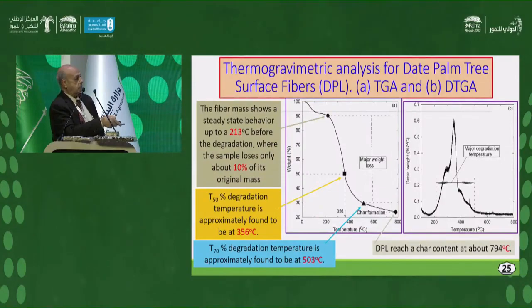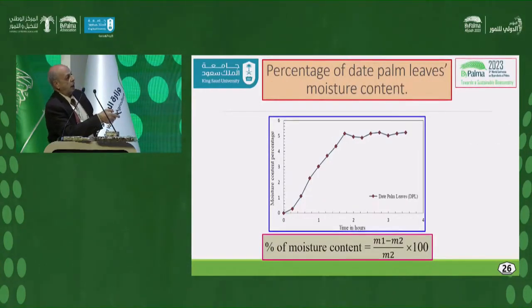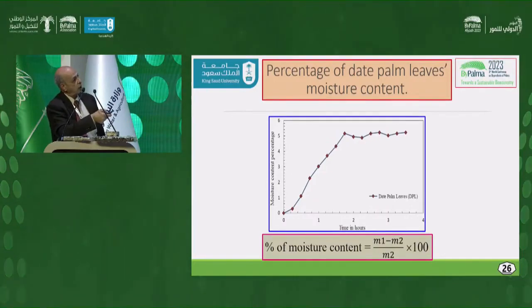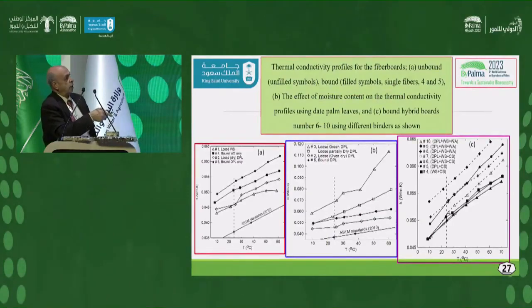And degradation at 70% at 503. So it means it is stable, so it can be used as thermal insulation. This is the moisture content experiment we have done to see how much water the fiber can absorb. So the moisture content is only about 5%. This is the thermal conductivity coefficient.